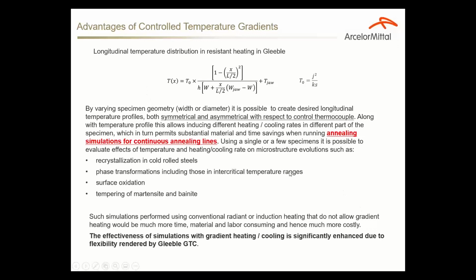Basically, this type of heating is very advantageous because we can change the geometry, the width of the sample, the diameter of the sample, and we can control the temperature distribution along the sample. We can control the gradient, we can control the cooling and heating rates, and that allows us to save time and material, especially for analyzing phenomena such as recrystallization, cold rolled steels, phase transformation, surface oxidation, martensite, and tempering of martensite. And I would like to emphasize that the effectiveness of such variable temperature simulation is much enhanced by the Gleeble GTC system. It gives us a lot of flexibility, and we're very happy that we have upgraded to GTC recently.